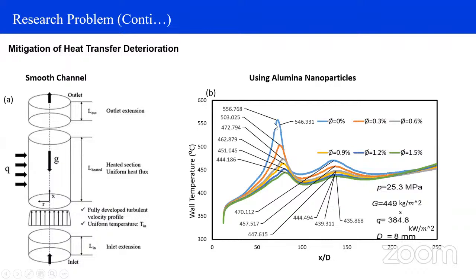472.794 at first peak. Same like at the second peak, when the concentration of nanoparticle is 0%, then the temperature is 470 point something. And when the concentration of nanoparticle is 0.3%, then the temperature is 457 point something. So it is clear from figure B, if we increase the concentration of nanoparticles, then the temperature at first peak and second peak reduces against growing strength of nanoparticle concentration. So we conclude that nanoparticles are very helpful to overcome the challenge to reduce the temperature inside the nuclear reactor.